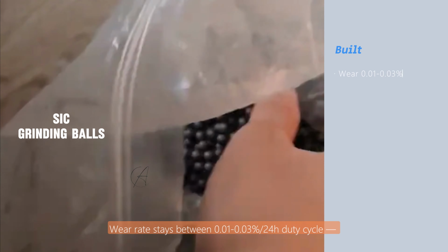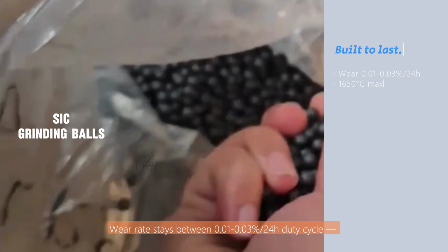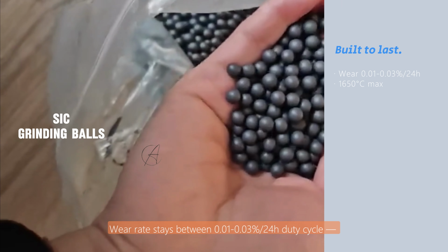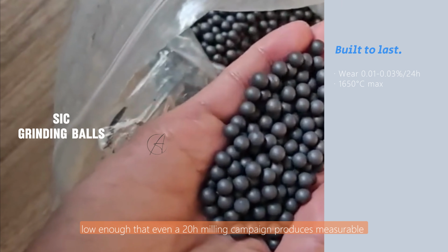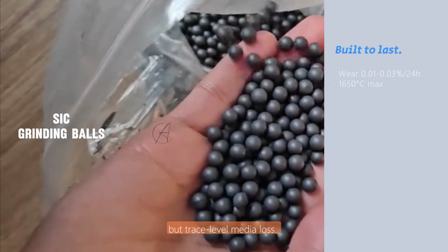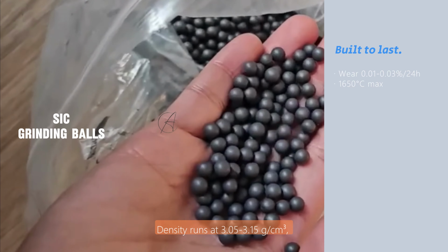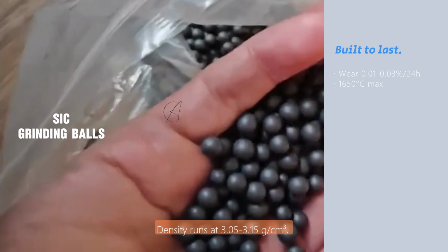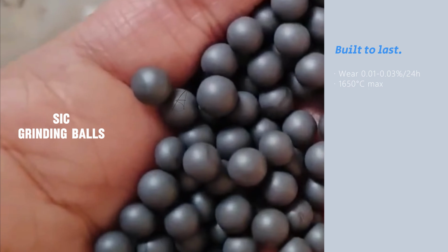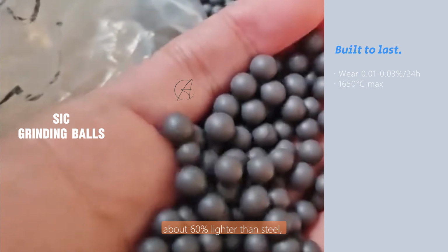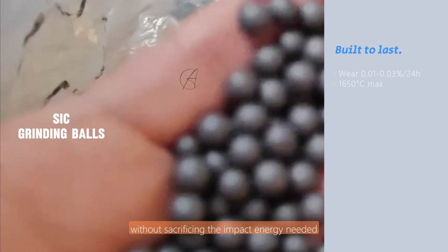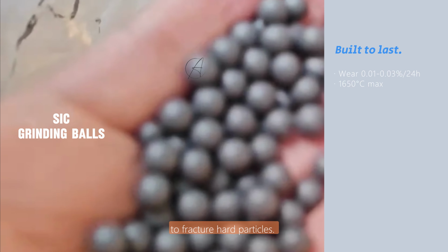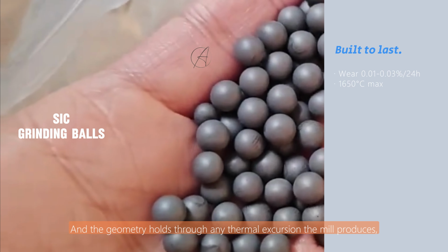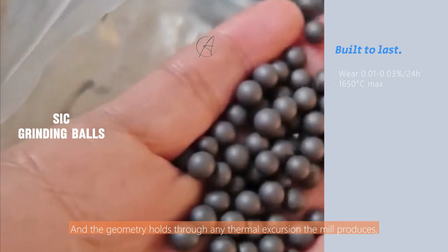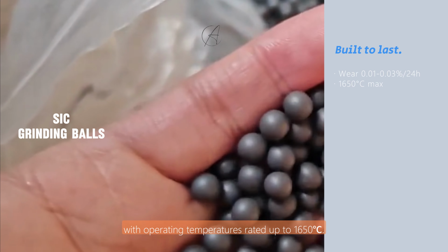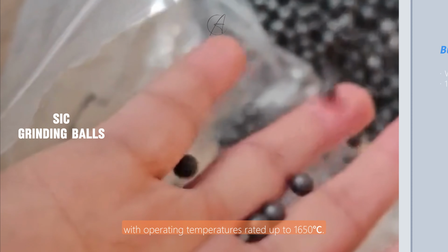Wear rate stays between 0.01 and 0.03% per 24-hour duty cycle, low enough that even a 20-hour milling campaign produces measurable but trace-level media loss. Density runs at 3.05 to 3.15 grams per cubic centimeter, about 60% lighter than steel, which reduces mill power draw without sacrificing the impact energy needed to fracture hard particles. And the geometry holds through any thermal excursion the mill produces, with operating temperatures rated up to 1650 degrees Celsius.